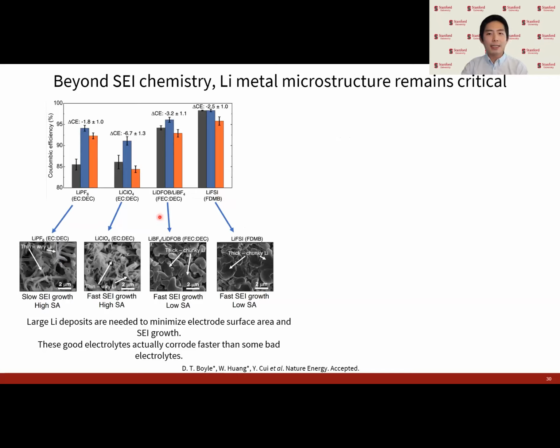But beyond the SEI chemistry, the lithium microstructure, shown here through SEM images, also plays a large role. So in these poor cycling lithium systems, like the PF6 and the perchlorate in the ethylene carbonate, we can see that lithium plates in this kind of filamentary or more wiry structure, which is going to have a very high surface area. While in the better cycling systems, such as the dual salt borated chemistry and this FSI and FDMB developed here at Stanford, lithium plates in this more kind of thick or pillar-like microstructure.